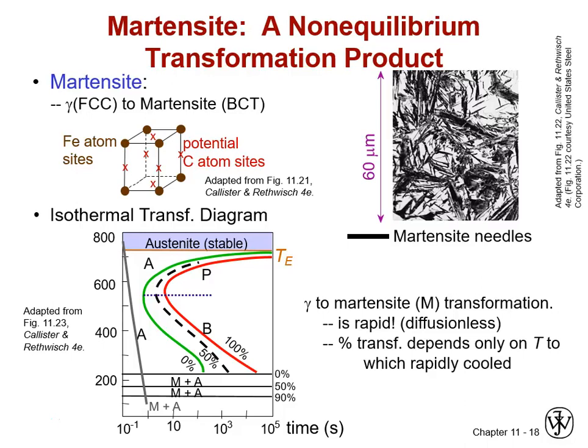And something to remember about martensite is because it forms spontaneously on rapid cooling, it's actually what's known as a diffusionless shear transformation, more like twinning than the diffusional transformations that we've learned about from phase diagrams so far. It's diffusionless because it happens literally because the carbon didn't have time to diffuse. So no diffusion is involved in forming martensite from austenite.